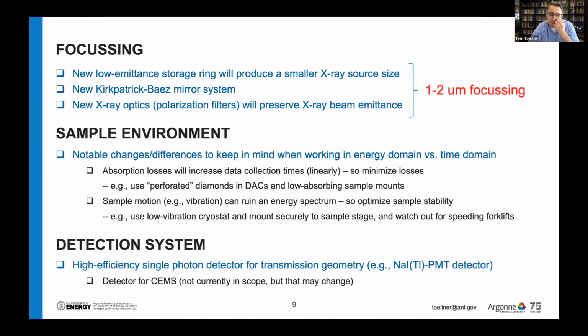Another issue is the sample vibration. Because the energy spectrum is based on Doppler shifting of the emitter, the sample needs to be stationary. And so vibrations can ruin the energy spectrum. So if you're using a cryostat, it needs to be a low vibration one to allow for that. And also samples need to be mounted to the stages more securely so that there is no motion. Motion along the beam is the motion that matters.